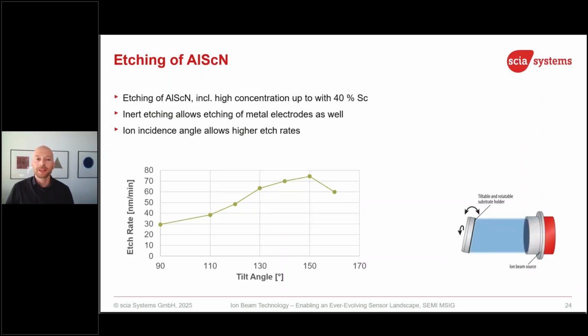The other example I mentioned already, aluminum scandium nitride. So normal aluminum nitride, you use an ICP etcher to structure it. For the highly doped aluminum scandium nitride, it's getting difficult. So you might have some scandium residuals on your wafer. But argon ion beam etching, of course, is working fine. Also here we see a strong dependency on the angle of incidence. So the higher the angle here, the higher the sputter yield or the etch rate is. And as a reminder, angle of incidence, we just tilt our chuck in front of our big ion beam source. At the same time, we have wafer rotation, which ensures a very good uniformity.